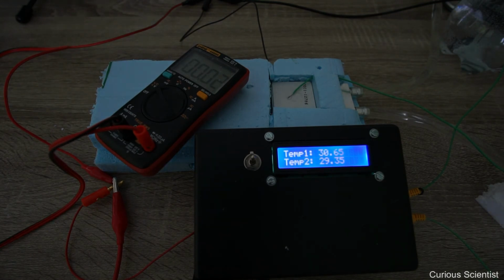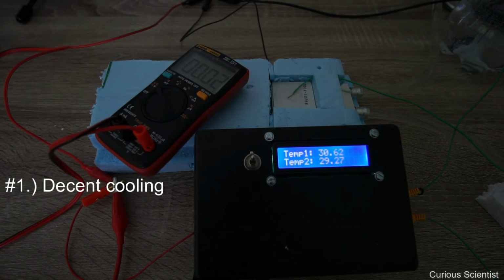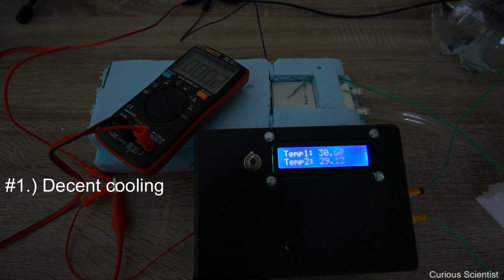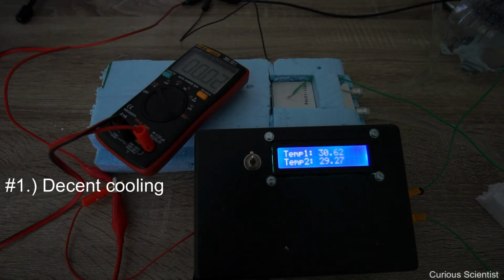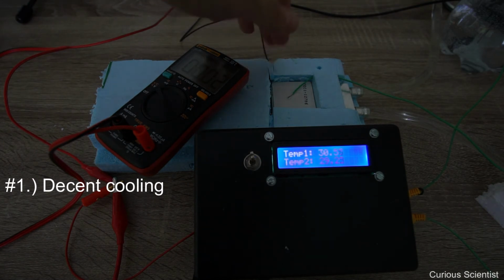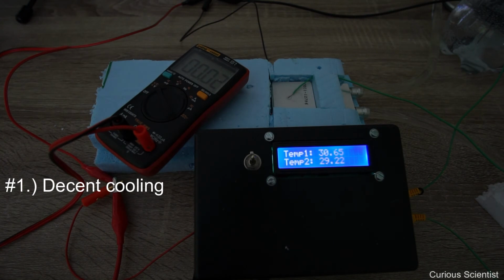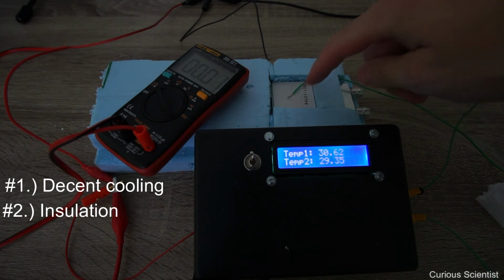So just to summarize my thoughts, you need a decent cooling to be able to go down to very low temperatures, and I suggest you use water cooling because, although it's a bit more messy because of the liquid, it is more silent and more efficient because of the heat capacity of the water. You should use some insulating material like I used, some styrofoam. You should use a very good connection between the block and the cooling element.